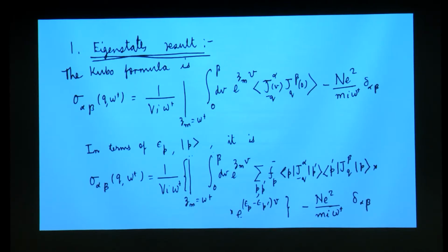Okay. So the first result which I am going to talk about is the exact eigenstates result, starting from the Kubo formula, which is the microscopic formula for the linear response of a system to an external electric field. So this is the conductivity in terms of, let us say, current fluctuations of the system. Now, if I write this in terms of the exact eigenstates and the energies, this can be written as some product of two matrix elements times some exponential factor, and an exponential factor coming from the Heisenberg time evolution of this current operator.